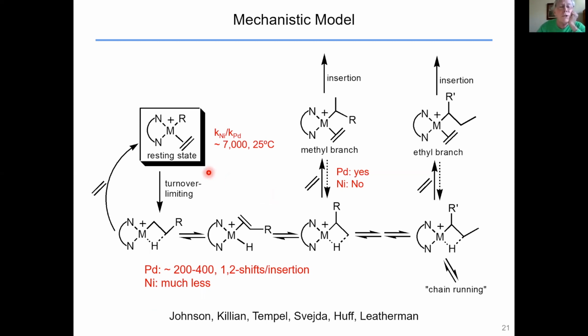You can observe the resting state by NMR spectroscopy, and the resting state of the catalyst is the alkyl olefin species. The turnover limiting step is the migratory insertion. So unlike early metal systems, the rate of chain propagation is independent of ethylene or alpha olefin pressure, but it's only dependent upon the rate of migratory insertion. It turns out that the ratio of the rates of the nickel insertion to the palladium insertion is about 7,000. So the nickel, as we've seen on the earlier slide, is far more reactive than the palladium system.